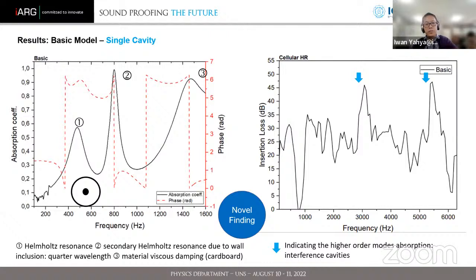You can see in this slide, we have 3 peaks. The first one is regarding Helmholtz resonance. The second one is regarding wall treatment, and the third one regarding viscous damping of the material. On the right side, you can see the blue arrow indicating a repetitive absorption phenomenon. It means that the interference cavities we put inside our model are working properly.